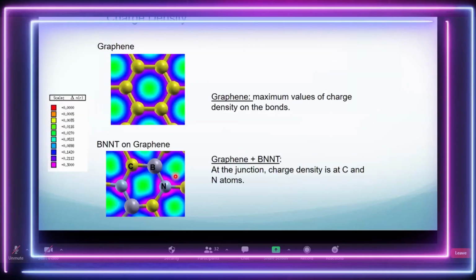First thing you look at is what is happening at the interface. What kind of bonding is going to happen? Is there any polarization? This is a pristine graphene sheet. You can see the nice electronic cloud at the benzene ring. This is the hexagon, and that shows the pi electron cloud. It's very, very flexible. If you bring in the boron nitride nanotube on top of it, you can see a polarization on the graphene. So indeed, the contact made in the experiment is influencing the property of graphene by polarizing the carbon atoms' electron density next to the boron or nitrogen atoms.